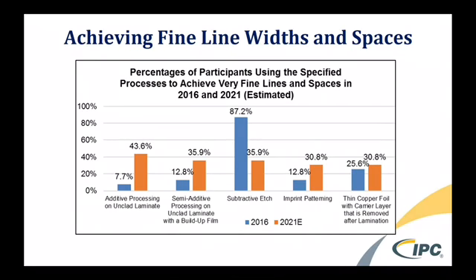Now, how do you achieve these finer line widths and spaces in addition to improvements in imaging? Well, for the longest time, our industry, as you can see smack dab in the middle there, used subtractive technology, basically laying down the image, exposing, developing, etching, and stripping, and etching away 1 ounce of copper, 1.4 mils, to define the pattern. But as we get into these finer lines and spaces and these requirements, it's going to take adjustments in the way we process printed circuit boards, and we see a lot of that now moving towards additive processing, which is basically building up your circuitry on unclad laminate, or you move into semi-additive processing, which is basically starting either with a very thin copper foil, or you can start with a 1 ounce or half ounce copper foil and etch it down part way, or you can build up your circuitry on a build-up film, such as the Ajinomoto film, and these give you very, very fine line opportunities for higher density and densification of circuitry.